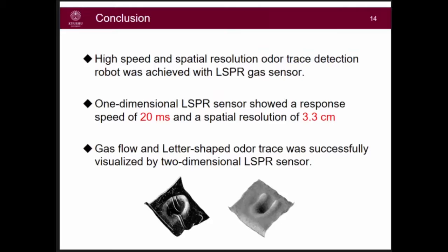In conclusion, we developed a high-speed and high-spatial-resolution LSPR sensor. The one-dimensional version showed a 20-millisecond response speed and a spatial resolution of 3.3 centimeters. Gas flow visualization and letter-shaped odor traces were successfully visualized with the two-dimensional sensor. Thank you for your attention.